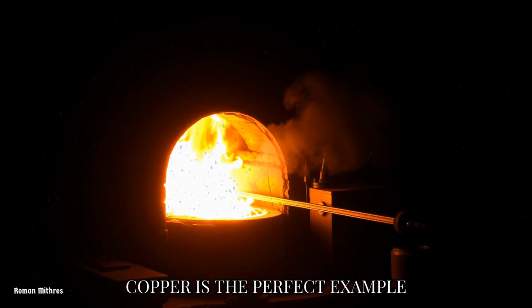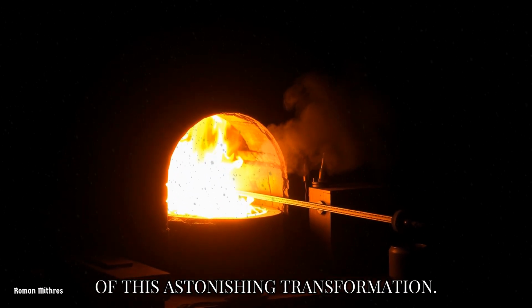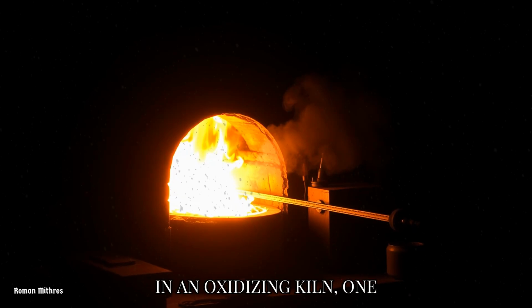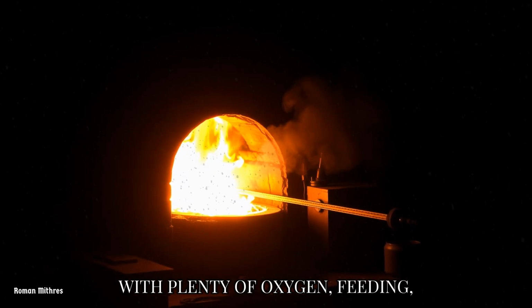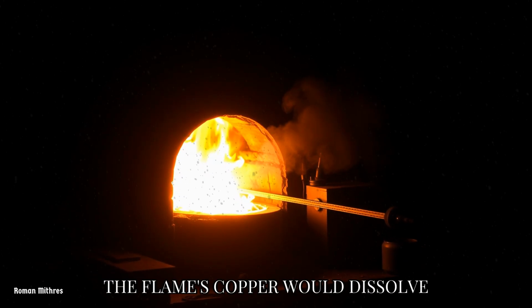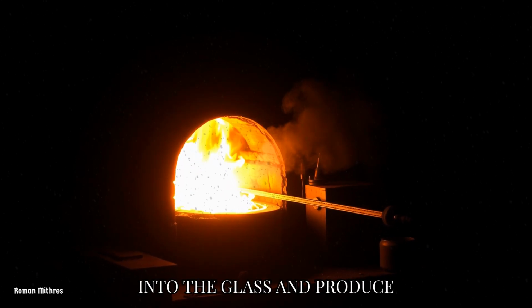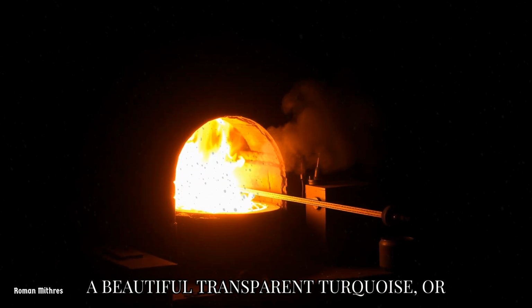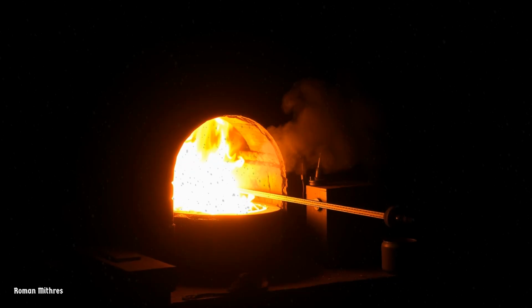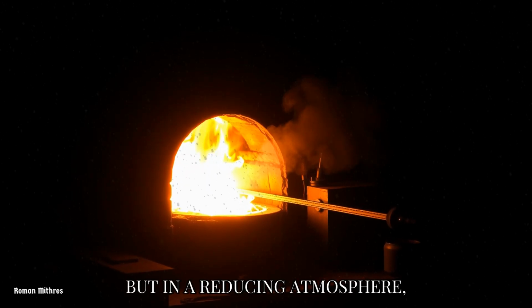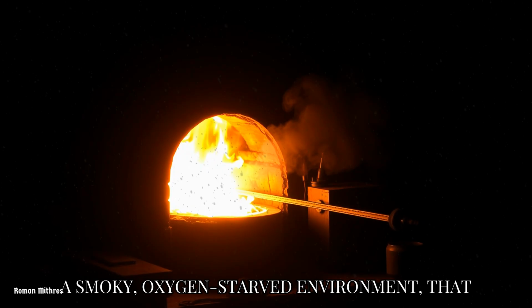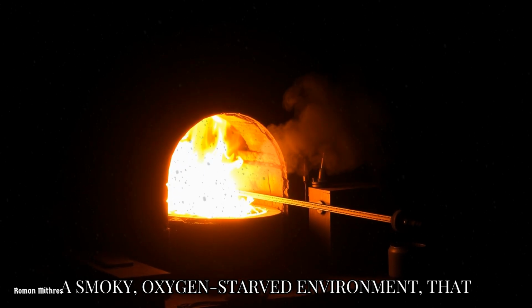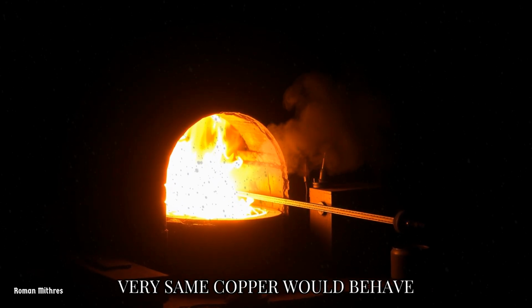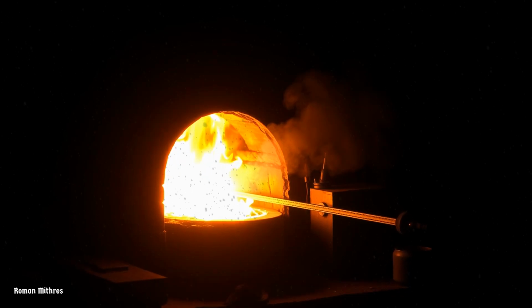Copper is the perfect example of this astonishing transformation. In an oxidizing kiln, one with plenty of oxygen feeding the flame, copper would dissolve into the glass and produce a beautiful transparent turquoise or light blue. But in a reducing atmosphere, a smoky, oxygen-starved environment, that very same copper would behave completely differently.